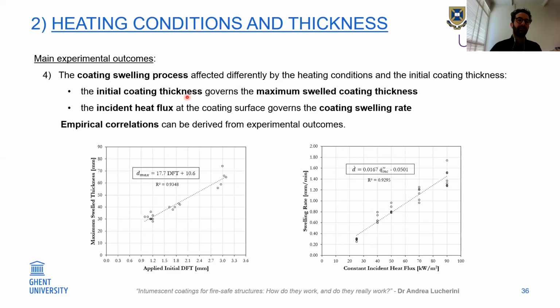Particularly the initial coating thickness that I show you here, the initially applied DFT, governs the maximum swell coating thickness. So based on the initial DFT, you can get a maximum swell thickness. Then the coating stops swelling, okay? And here I mainly create an empirical correlation between the initial applied DFT and the maximum swell thickness. On the other side, the incident heat flux at the coating surface governs the coating swelling rate. So for a high heat flux, higher temperature, high heating rate, I have a faster swelling coating.